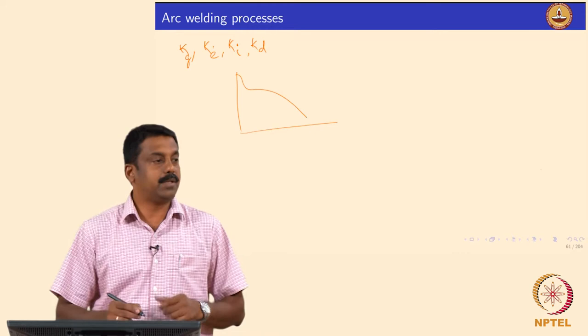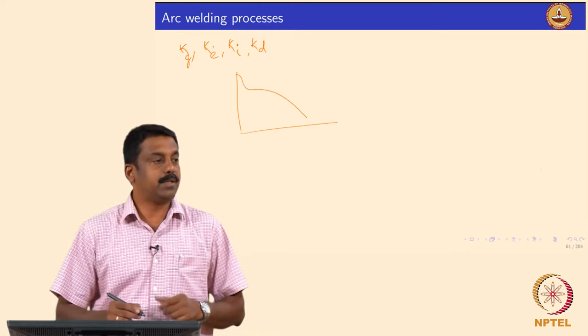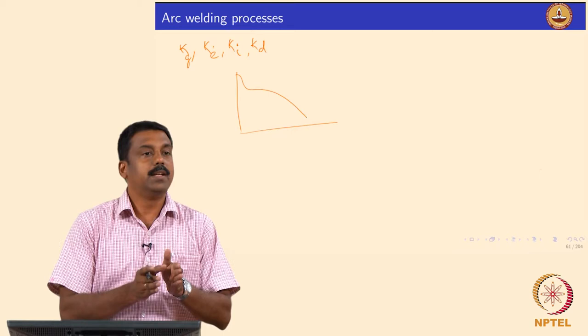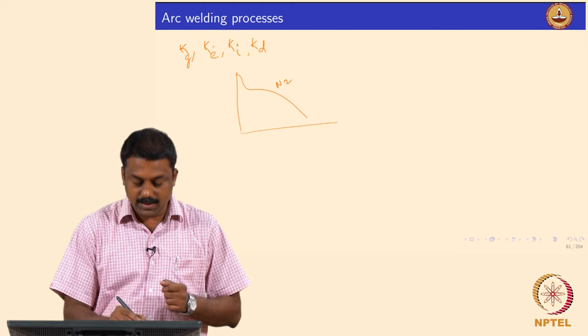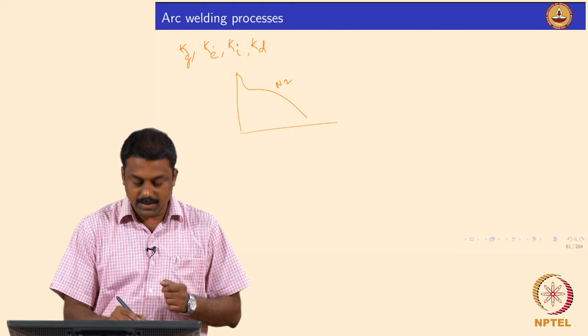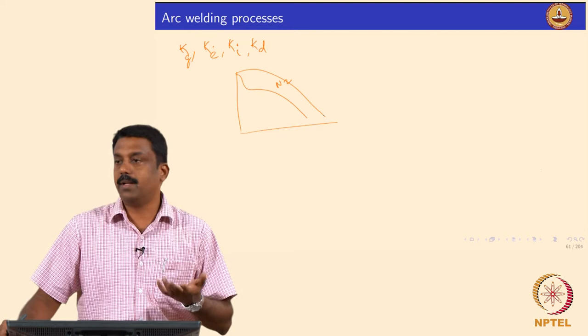This shouldering effect is especially seen in diatomic gases because of dissociation — the heat transfer by dissociation means that the dissociated gas can travel elsewhere, recombine into a diatomic gas, and during this process the heat is transferred. In contrast, for monoatomic gases like Ar, such a shouldering effect is not present because the dissociation phenomenon does not occur.